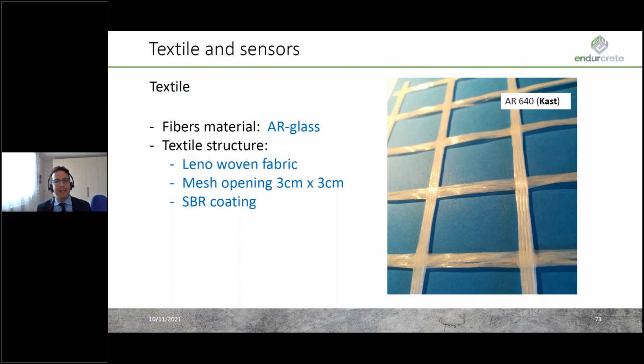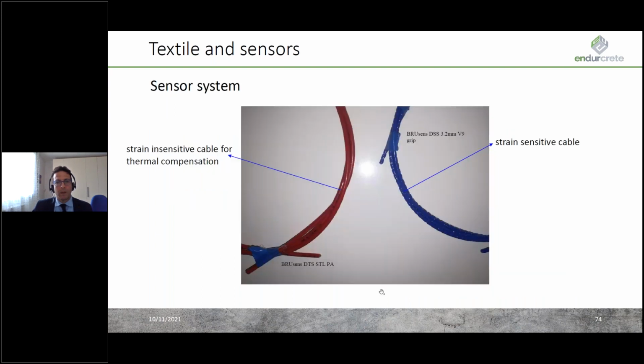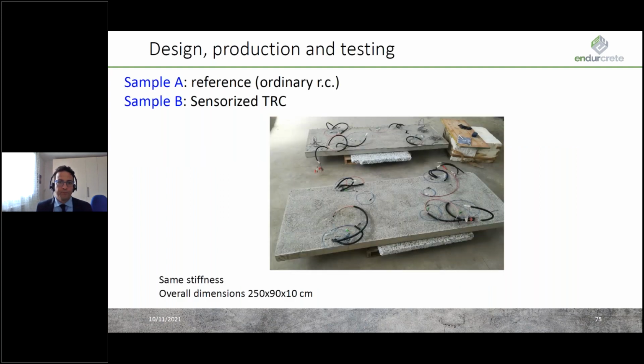The textile is made of alkali-resistant glass with a mesh opening of 3 centimeters, while the sensor system is made of 2 distinct cables. Here they are. The blue one is a strain-sensitive cable with roughened surface for a better adhesion with concrete, while the red one is a strain-insensitive cable for thermal compensation.